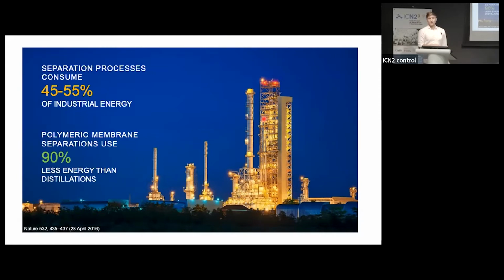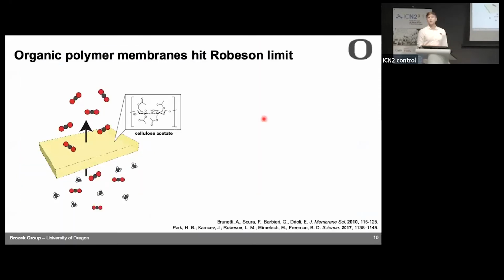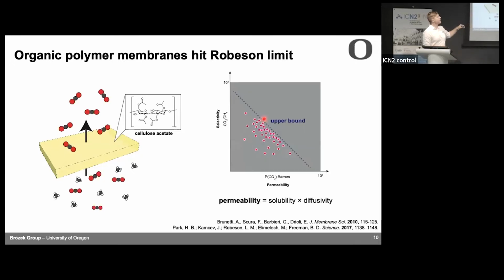So people want to make membranes. And the way that people make membranes now is mostly using cellulose acetate. And that's nice because cellulose acetate is readily abundant. It's relatively inexpensive. But the issue with cellulose acetate is it's difficult to chemically functionalize. And so when people use cellulose acetate for separations of CO2 versus methane, for instance, they notice that the performance of these membranes hits an upper limit.